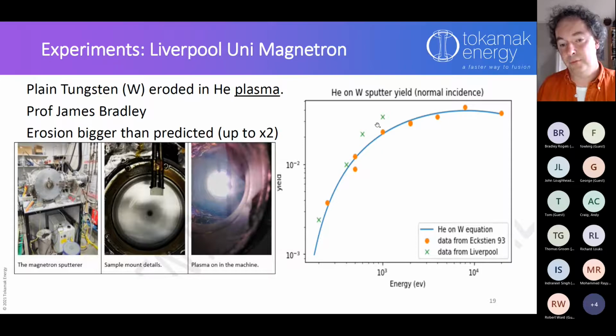So this one that's probably the worst one out is out by a factor of 2. That's not bad. Again, they're a bit bigger than the prediction, but if we can get it within a factor of 2, that's actually quite promising, because we need to know if it's going to be 1 day or if it's going to be 1 year. So if it's a day, actually, if it's half a day or 2 days, it doesn't really matter. It's still a really short time.